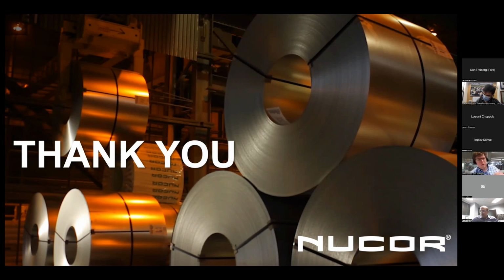The ratio of busheling to number 2 scrap or shredded scrap will vary, but it'll also be higher busheling, or pre-consumer scrap content, for charges that don't have DRI, because DRI doesn't have any residuals and we'll take advantage of that. Whereas the mills that use DRI will use a much higher post-consumer scrap mix, more shredded.